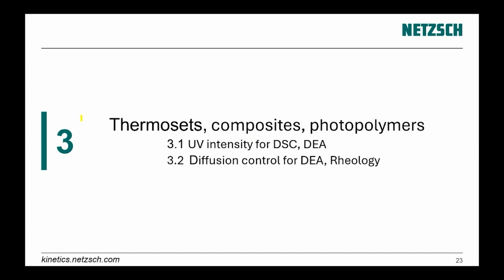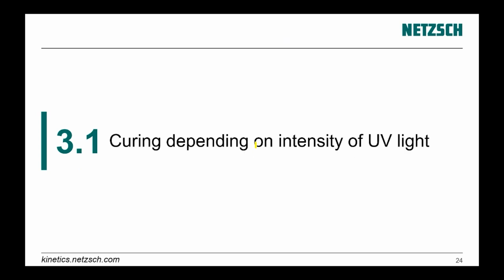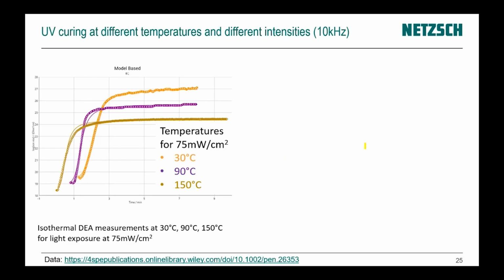The next part is thermosets, composites, photopolymers. Here we have again an example with a second parameter, and the second parameter is UV intensity, where the reaction rate, the curing reaction, depends not only on the temperature, but on the intensity of UV light. Here, the first set of data is our isothermal data, which are measured on DEA, dielectric analysis. Here, vertically, we have the log of ion viscosity. At the beginning, it is low, and then during the curing, the viscosity of the material goes up, and the ion viscosity of the material increases